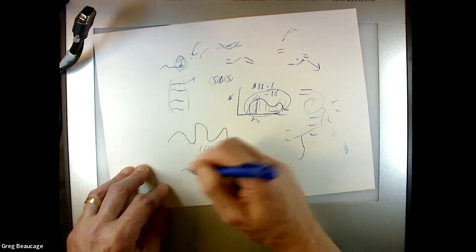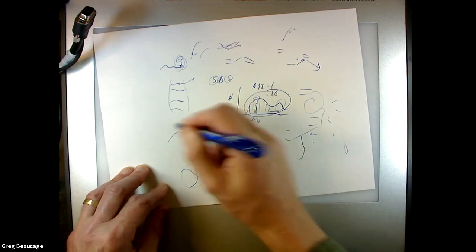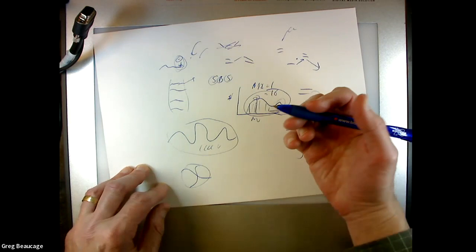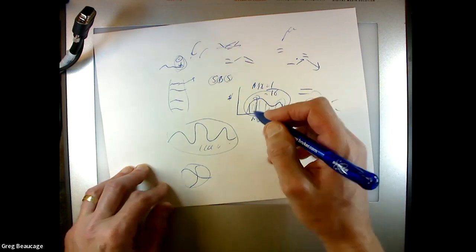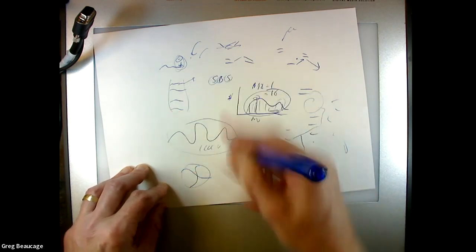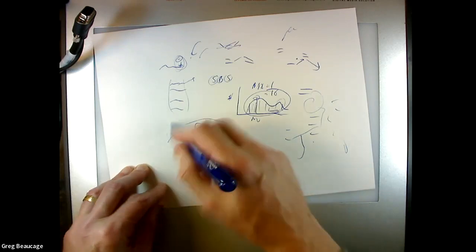So if you have a chain like this that's 100,000, and a chain like that that's 100,000, this one will have a smaller hydrodynamic radius than that one. But the light scattering will give the same number, while the radii of gyration will be different too. So if you have three or four detectors, you start to be able to tell the difference between these things somewhat.